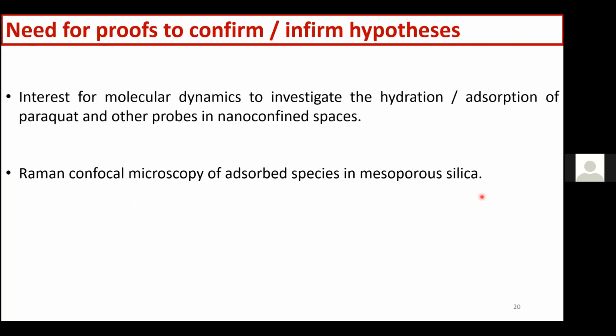We would need to perform some molecular dynamics to investigate the hydration and adsorption of paraquat and the other probes in these nano-confined spaces, and the effect of the interaction of the electrolyte ions with the probes. Maybe also looking locally at the adsorbed species, and which chemical groups of the adsorbed species are being affected by the silica film, could give us some information there, looking at intermolecular interactions. So these are things that we had planned to do, but we were still running behind because of the lockdown, and we haven't got back to full experimental capacity yet.